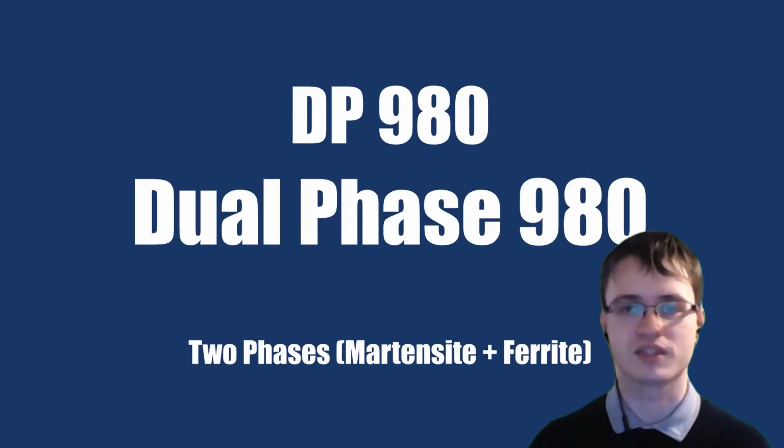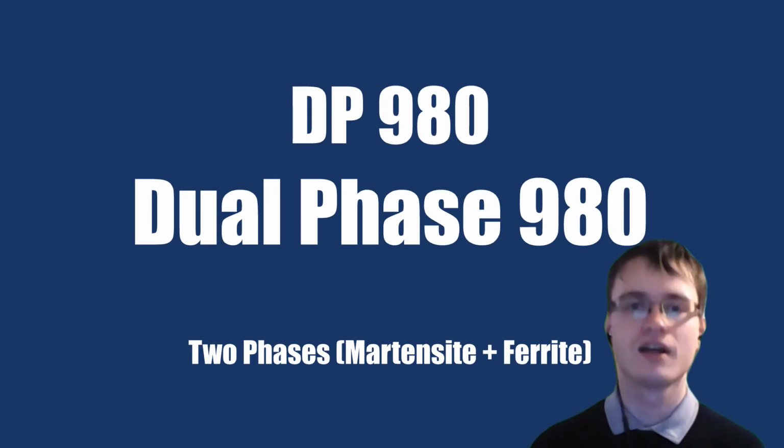This microstructure is comprised of two distinct phases called martensite and ferrite, and it's these two phases which give DP980 its name. Ferrite is a soft phase of steel with low strength and high ductility, whereas martensite is a hard phase with high strength and low ductility.